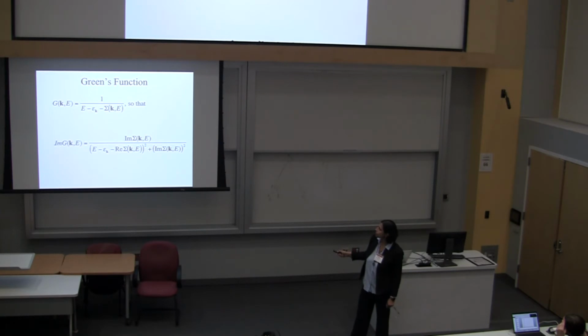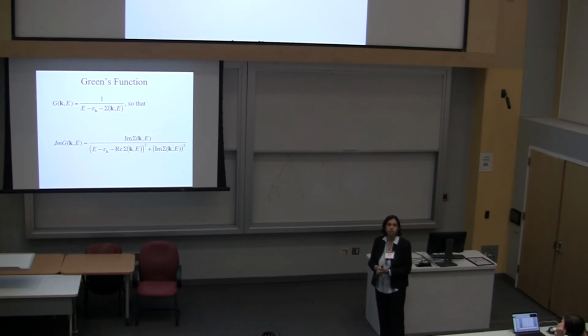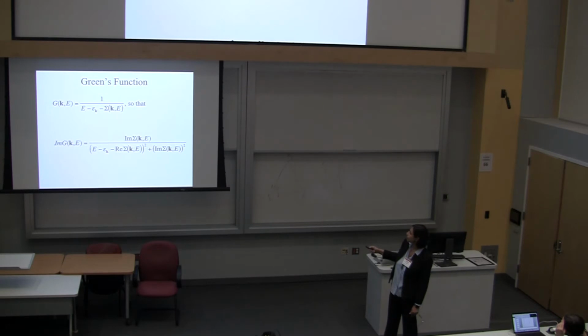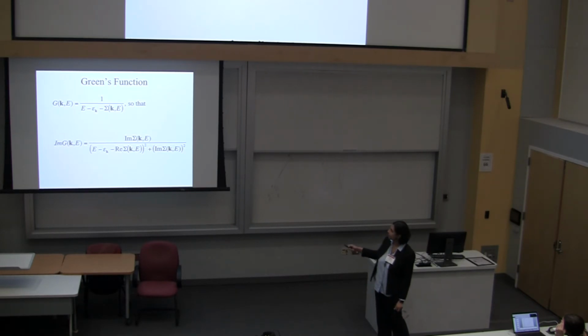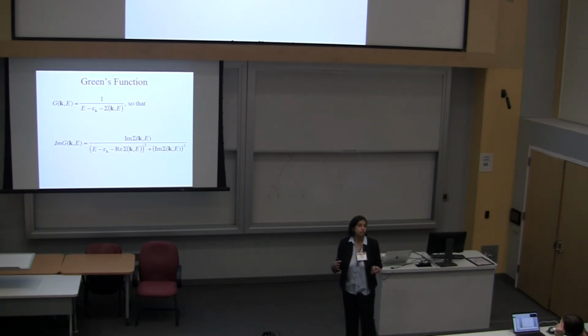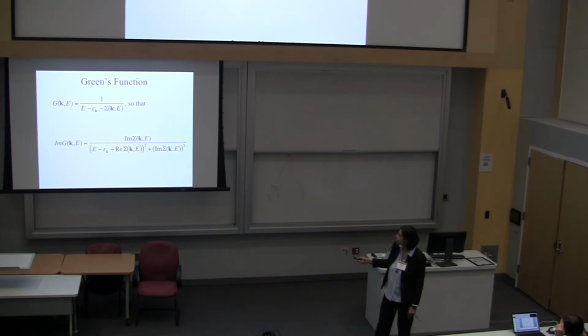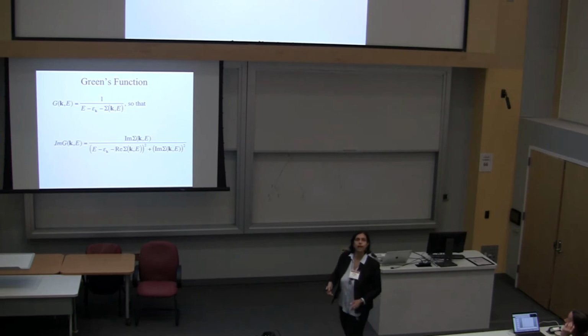We are measuring the imaginary part of the Green's function, which is the density of states. And if you have electron-phonon coupling or any interactions of any kind, all of the interaction effects can be encoded in something called the self-energy. So the imaginary part of the Green's function looks like this. This E_k is just the bare dispersion. This is the real part of the self-energy. This is the imaginary part of the self-energy. So what this is telling you is that the imaginary part of the self-energy broadens things. So if you have interactions, things get broader. The real part of the self-energy shifts things. So if you had a band at some momentum k and energy E, the real part of the self-energy shifts it around a little bit.